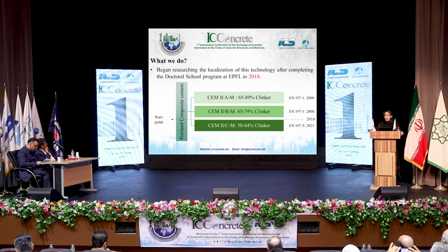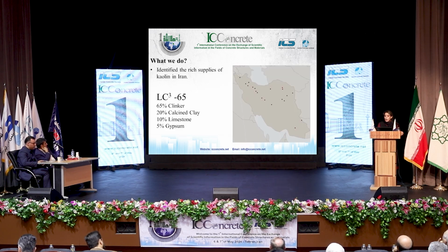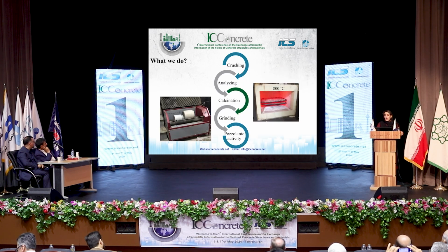But what we do in Iran, we started researching the localization of this technology after passing doctoral school at EPFL in 2018, which was before the EN standard in 2021. So we decided to produce LC3 65. We identified the rich supplies around Iran and we gathered samples. Here you can see our process to produce a laboratory scale of limestone calcined clay.